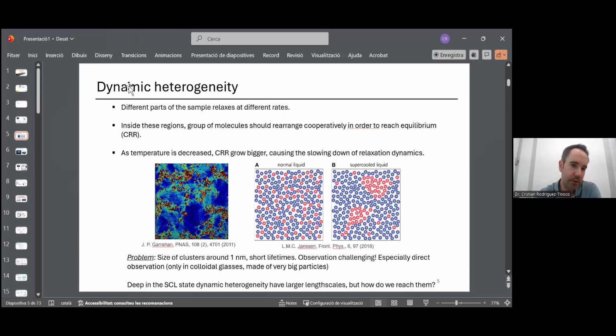So I was saying, this exponential increase in the relaxation time is considered to be a consequence of the formation of these cooperative rearranging regions, which are clusters of molecules or atoms that relax cooperatively. These cooperative rearranging regions grow larger and larger as the temperature is decreased. So this is why we have this increase in the relaxation time.